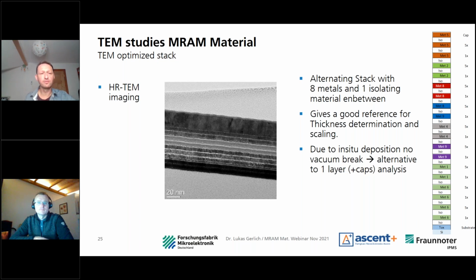Of course, also with electron microscopes like high resolution TEM, we can produce special, very big stacks without breaking the vacuum. In this case, between every single metal layer and also between thickness splits between metals, we have isolating material in between to enhance the contrast for the TEM measurement, and therefore we can have a good reference and see the thickness by only one TEM shot, because as most of you know, it is quite high effort, and due to the in situ deposition, we have no vacuum break. The alternative would be to deposit only one layer, with a cap, and have one analysis for every material.